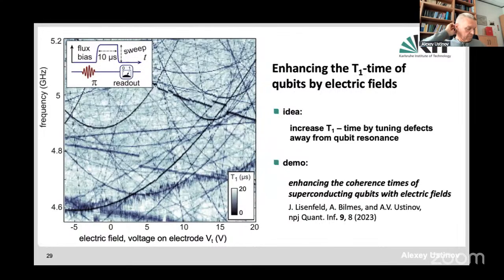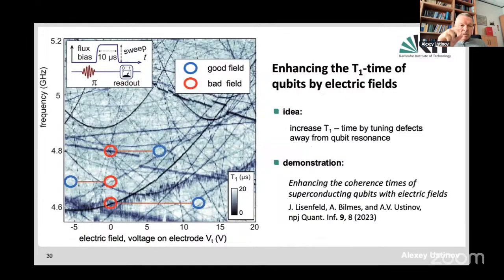Now, for the last couple of minutes, I want to show one of the more recent developments. We came up with the idea of how one can use the control of the defects by electric field to improve the quality of the existing circuits. Suppose that you have some regions where the superconducting qubit is suffering from a defect at some frequency. When applying the electric field, for example, to this red region indicated here by the red circle, one can apply an external electric field to tune the defect away and then find a very nice white spot with high coherence. That's where the qubit properties are significantly improved.